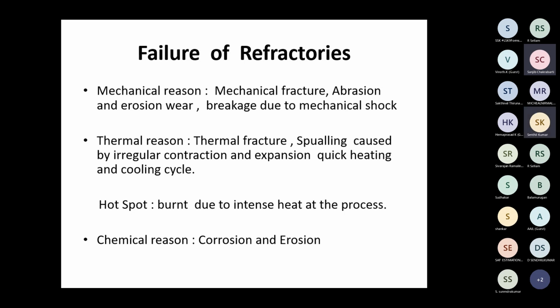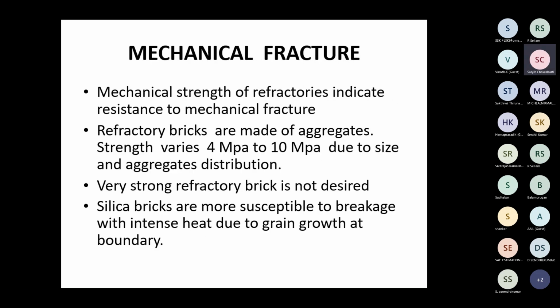Hot spot burn is due to the high heat process, particularly in the arc furnace, where the arcs are. There is a hot spot near the inside. The chemical reason is the most important part, as I told you: corrosion and erosion. Mechanical failure, as I explained, relates to mechanical strength, which indicates the resistance of refractories to mechanical fracture.